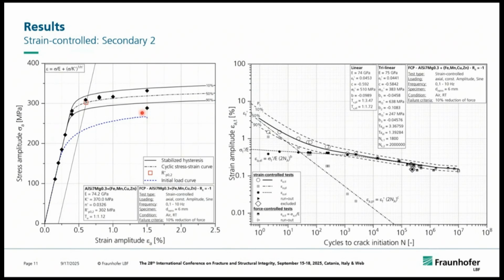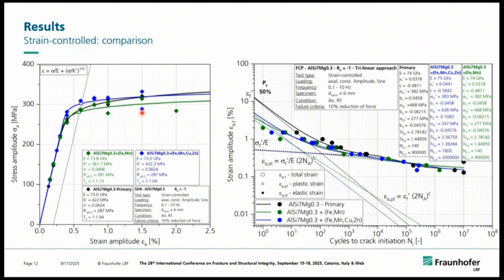When we look into the comparison of those curves, primary, secondary 1, secondary 2, we can state that we end up in the stress strain regime more or less in the same region. When it goes over to higher total strains, then there is a bit more performance in the primary alloy, and so we see it also for the strain life curve. So in the strain life curve, we see that we have some number of cycles more to failure in the low cycle fatigue regime. So as I said, the elongation at break and the higher ductility play a role here also in the evaluation of those strain control tests.